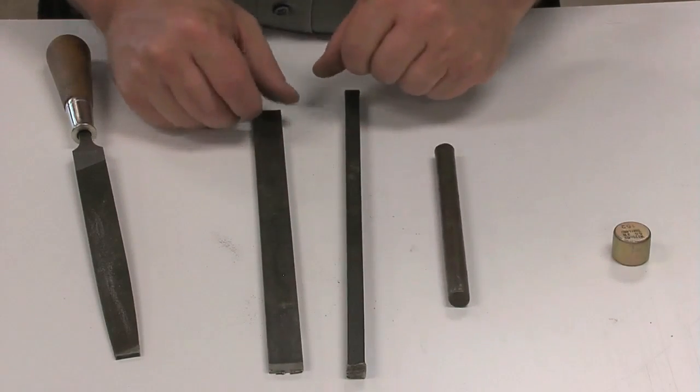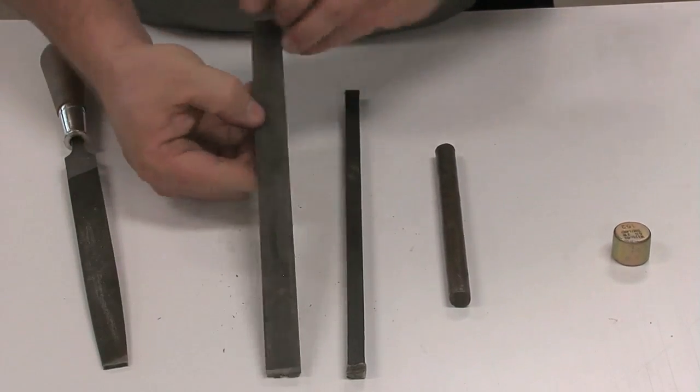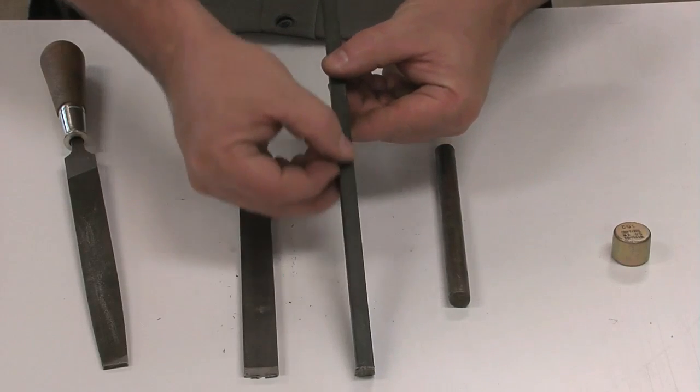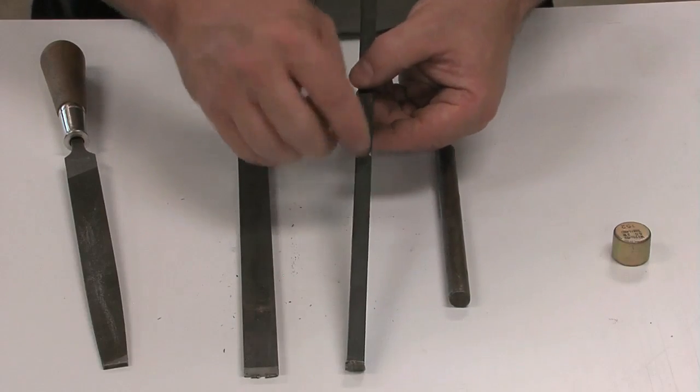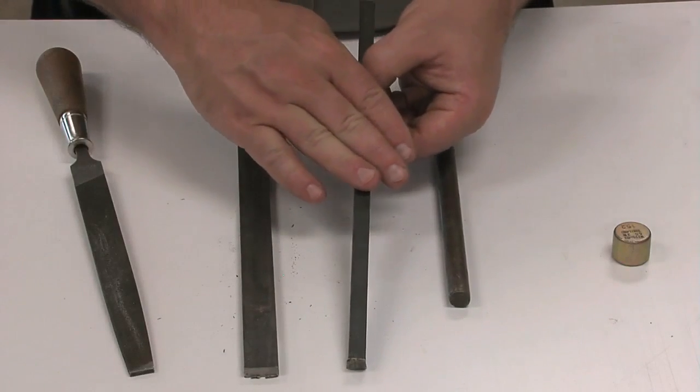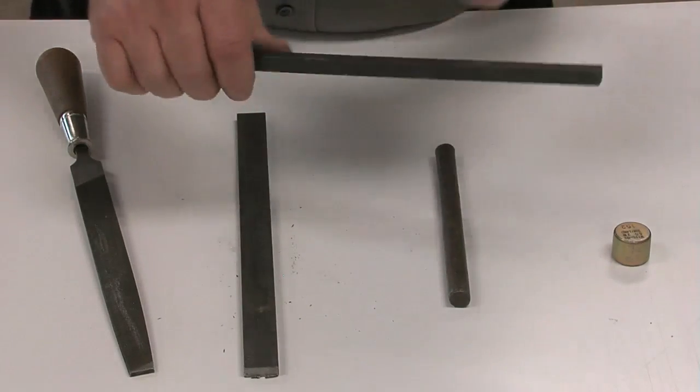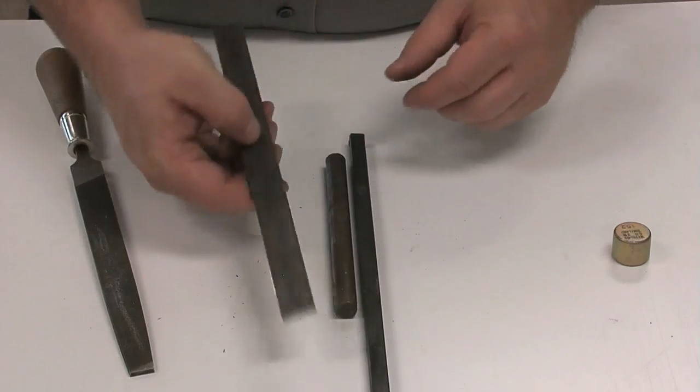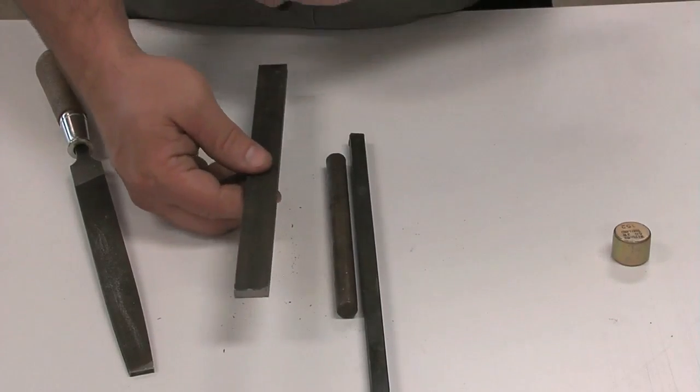You'll see two basic types of steels. This is called cold rolled in that it has a fairly shiny surface from the factory. That's opposed to hot rolled steel that actually has a layer of what's called fire scale, which is a chemical that bonds to the outer surface. Fire scale tends to be very hard, hard to file through, hard on cutting equipment, but it's still steel. It just has that dark color to it. Steels bend but are very rigid. They tend to be about the same weight as far as density as stainless, much heavier than aluminum.